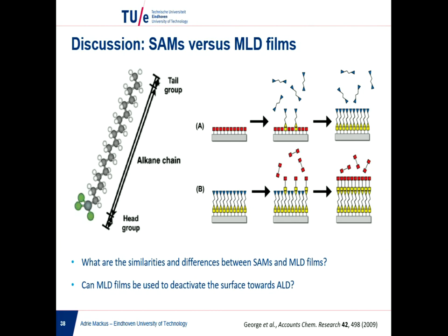Do you think this will work, or are there any limitations? Maybe I should look at the more senior table here. I have my doubts myself. It might work, but it looks so complicated. So I think one of the limitations is, well, the nice thing about these SAM monolayers is that if it's one molecule, and if it's ordered, then only this part is reactive and reacts to the surface, and the rest is inert to your ALD chemistry.